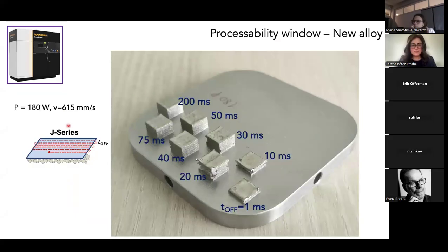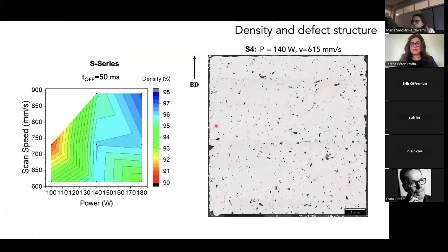So this was the first experiment. This is what we call the J series, but basically we took some conditions corresponding to group A in this processability window. And then we tried to manufacture cubes using increasing time delays from default to 200 milliseconds. What we could see is that even in these alloys that have a much higher glass formability, we still need some time delays in order to retain the shape. So we cannot work without time delay. So we fixed a time delay of 50 milliseconds, and then we explored the processability window.